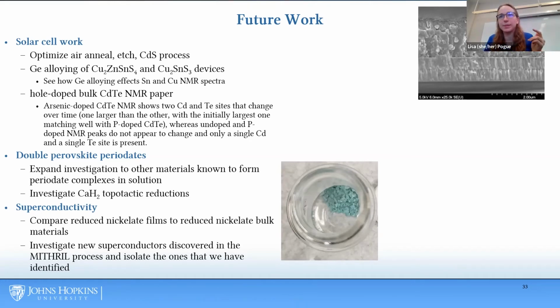And through this process, I identified a metastable mechanism that is causing the hole doped cadmium telluride, when it's doped with arsenic, to degrade. And this mechanism doesn't seem to be present in phosphorus doped cadmium telluride. There's still a lot of questions about the source of this, but this, in my understanding, is the first thing that has shown that there is this degradation process that happens over a several month time period.